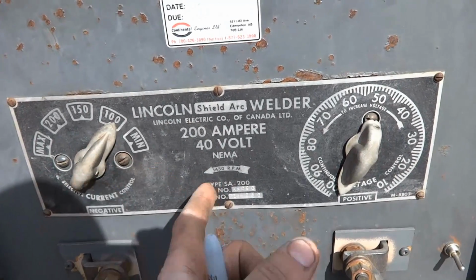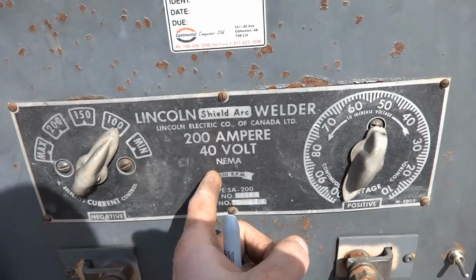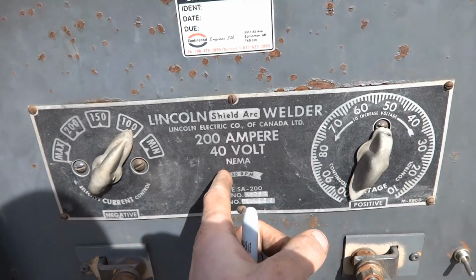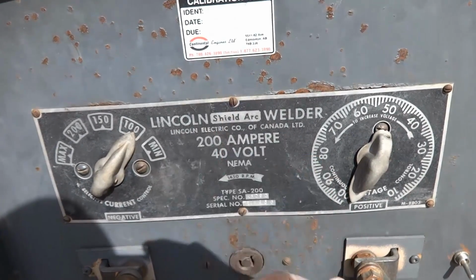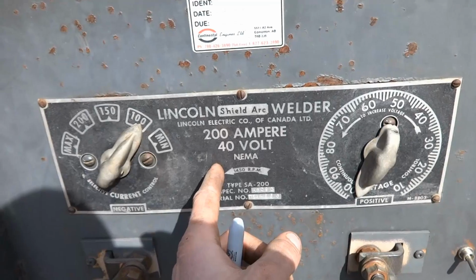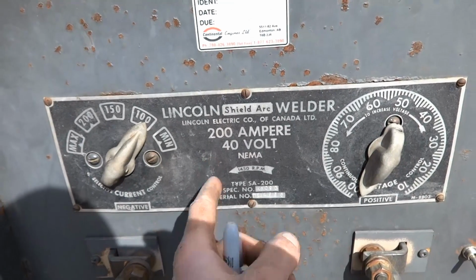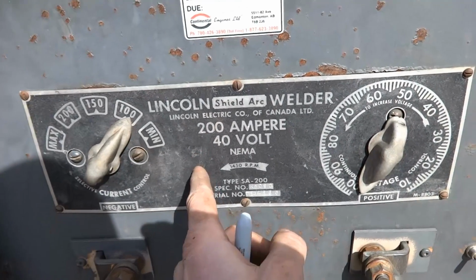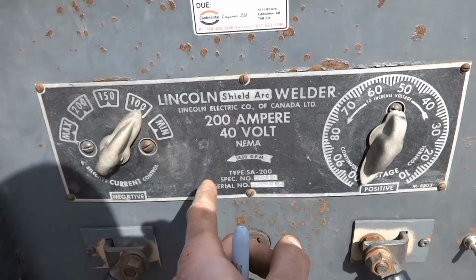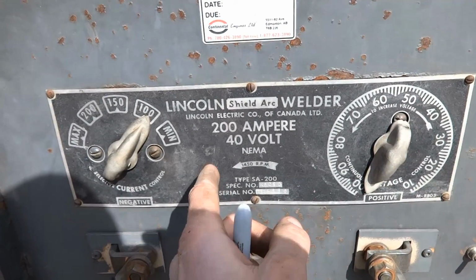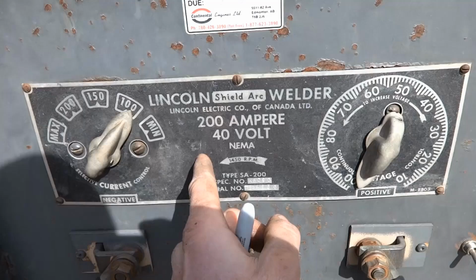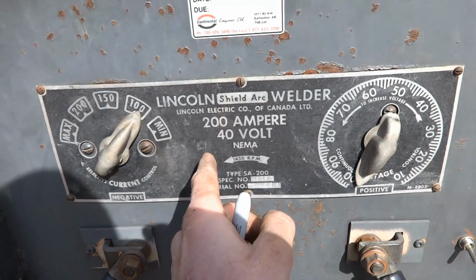Anytime you accidentally touch the pipe, the electrode will snuff out. Sometimes it'll reignite and the welder will keep welding. Every time it reignites, it leaves porosity. It leaves porosity because the electrode snuffs out, reignites again, and the tip of the electrode is bare metal, so it'll leave surface porosity. That's where you get your porosity from.